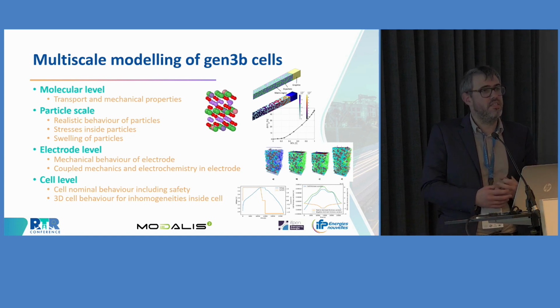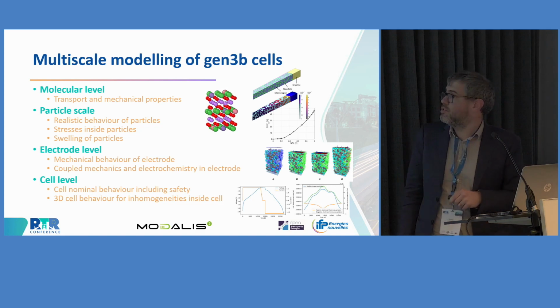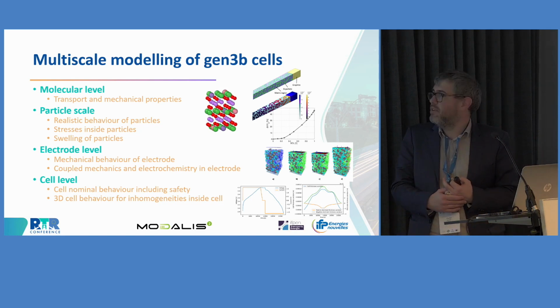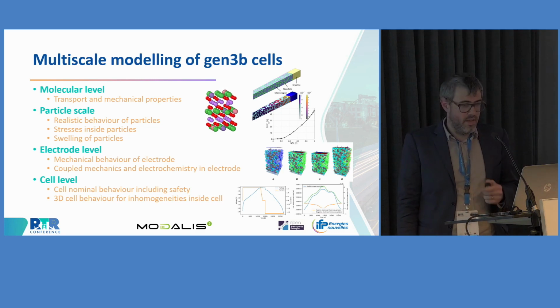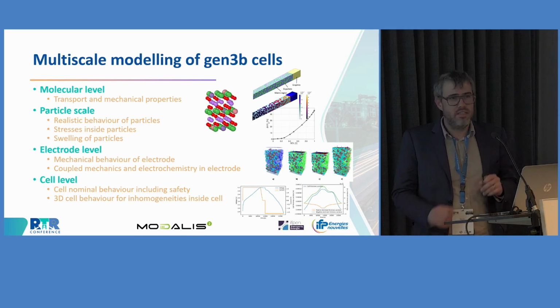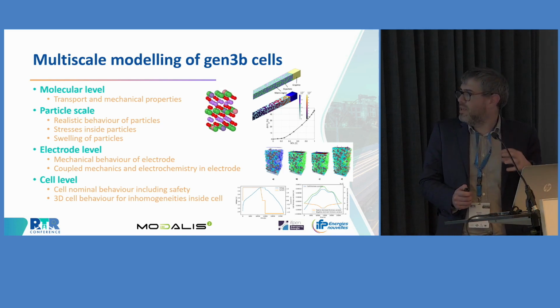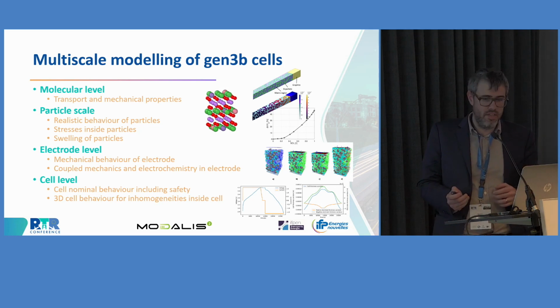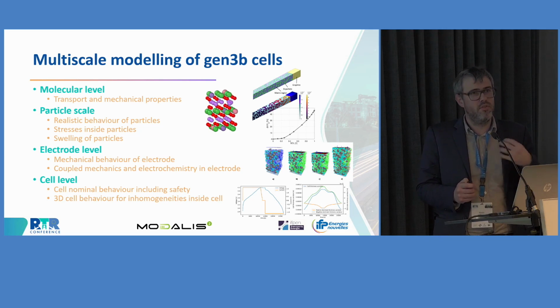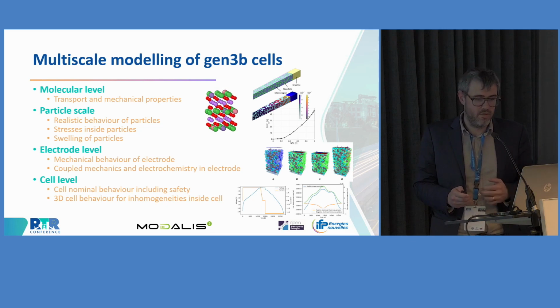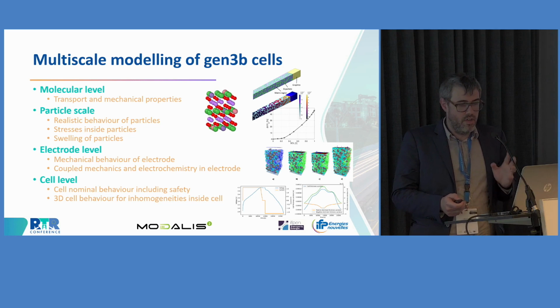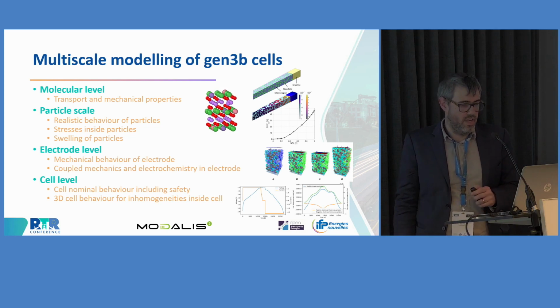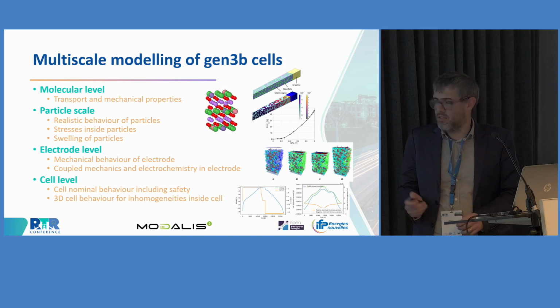Then at the particle scale, as I said, we had realistic behavior of the particles, and we were able to compute the stress generated in the particles due to the swelling of the materials. And of course, the swelling of the particles, as we can see here, was also evaluated thanks to this FEM simulation. At the electrode level, we modeled the mechanical behavior of the electrode with discrete element modeling. As we see here, the aim of this modeling is to see the swelling of the electrode during cycling, and also to monitor the bond damage in order to evaluate how much active material was lost during cycling due to mechanical failure. And finally, at cell level, the cell nominal behavior, including safety, was evaluated thanks to the models, and also thanks to Siemens SimCenter tools, we are able to do a 3D modeling of the cell in order to monitor the heterogeneities.